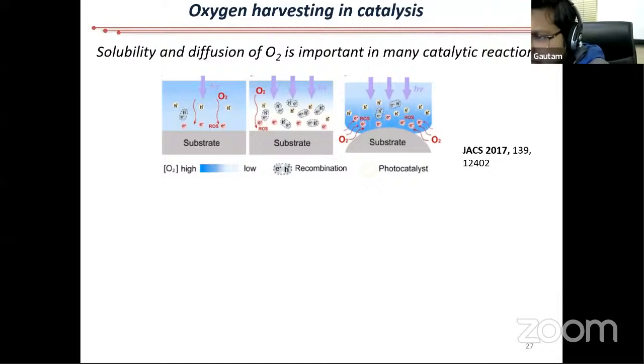So if the oxygen gets used up, then the next oxygen doesn't go to the catalyst. It takes a long time to go, and it doesn't get stabilized. It becomes more complex. But one of the things is for sure, if you can put a lot of oxygen on a catalyst, the reaction will become fast. So we need a catalyst which can actually take a lot of oxygen. And such materials are, as far as I know, rare, which can act as a catalyst and at the same time take a lot of oxygen.